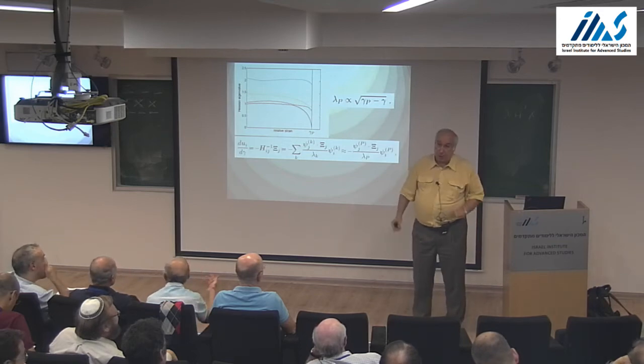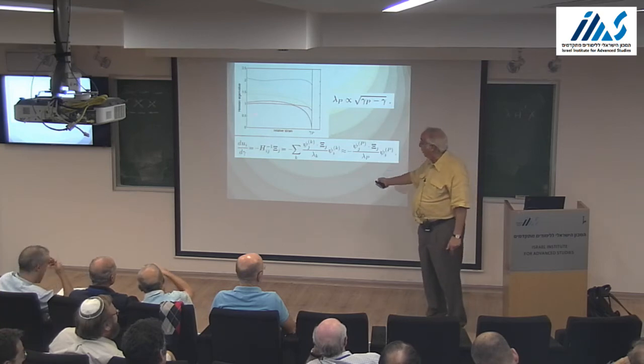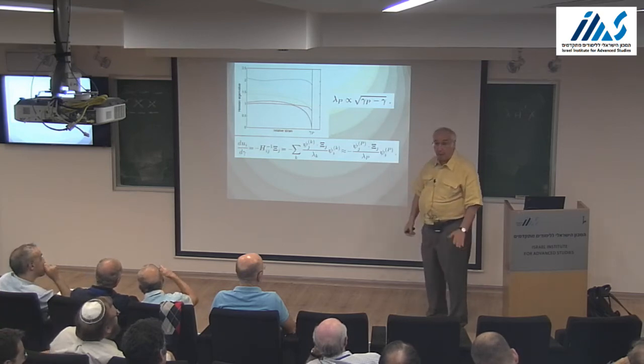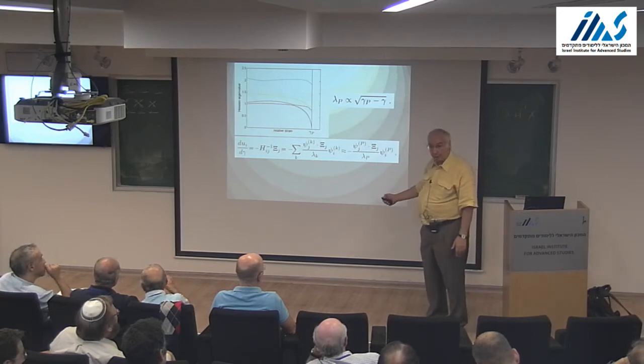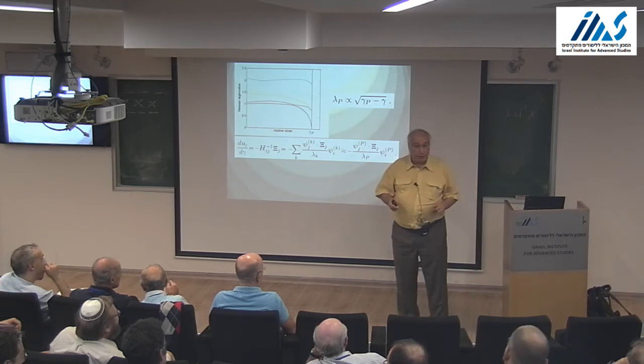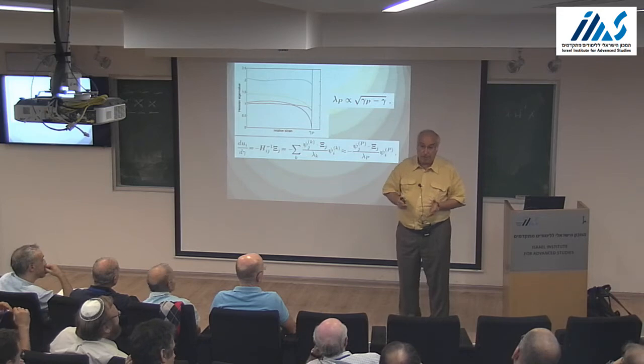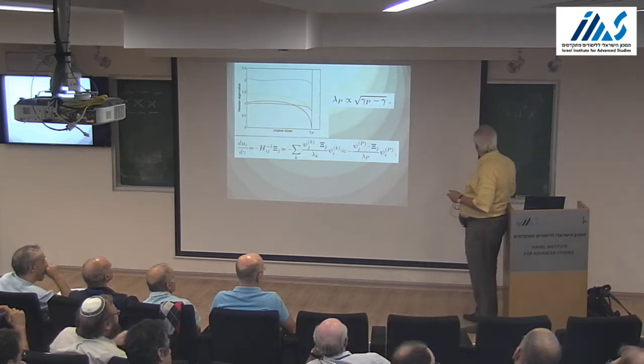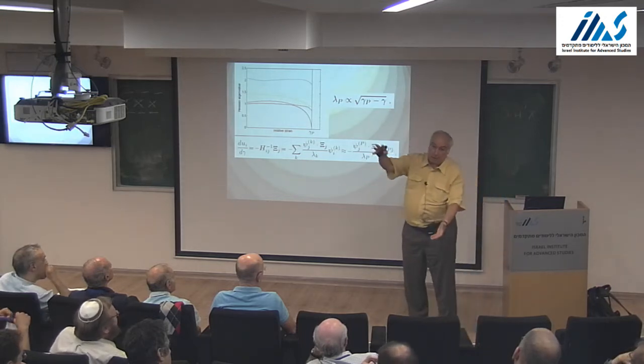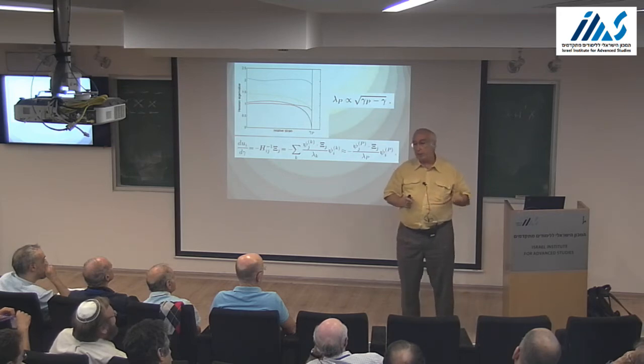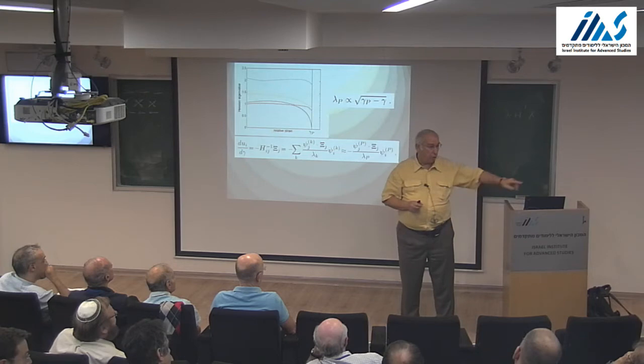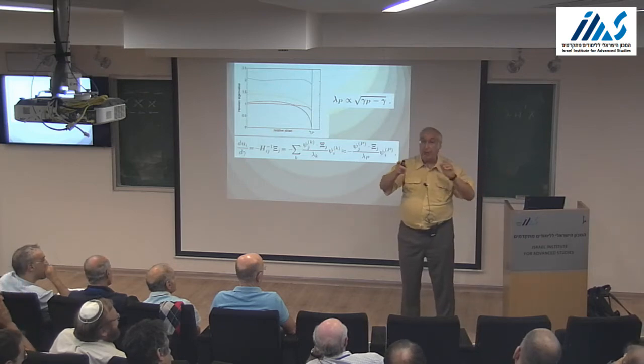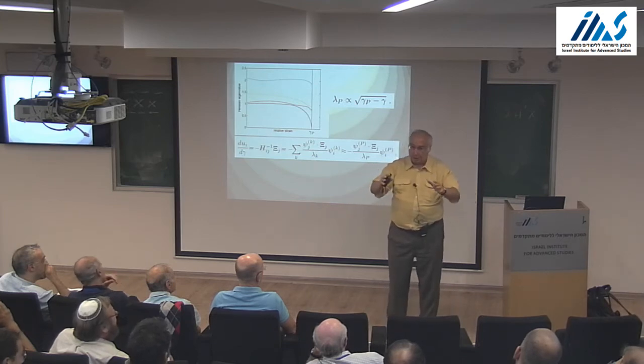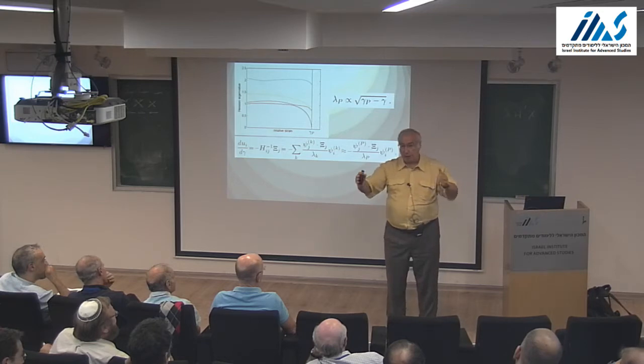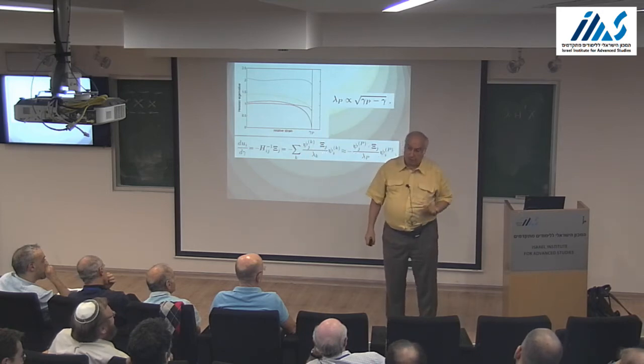This is an interesting issue, the existence of these lambdas. You have to be very careful because this is for a small system. When you have a large system, they begin to accumulate, and you have a density of them. And then the question is, are your moduli at all defined? And it's very interesting to understand that even though the shear modulus has an H^-1, has 1 over lambda in there, and all the lambdas are coming close to 0, it still exists. And the reason is because it's protected by the density. This is a work of Idan and George, etc., that we did, and you can show that the shear modulus still exists. In what sense? That if you look at a small system, the shear modulus, of course, has a distribution. You make larger and larger systems, the distribution becomes narrower and narrower and becomes a delta function in the thermodynamic limit. Not so for any higher order modulus.